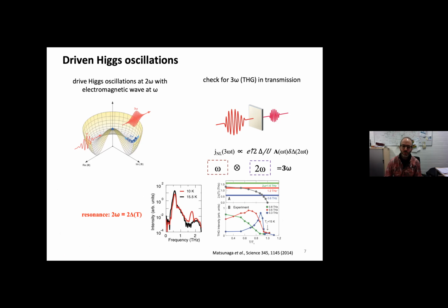And experimentally in the niobium nitride, this was also shown. So here you see this response of the system above TC in black, and then below TC. Really above TC, there's only a response at the driving frequency. And then when the system becomes superconducting, there's a characteristic third harmonic generation that comes out in these systems. And looking at this as a function of temperature, one indeed sees there is really a resonance behavior when this 2 omega equals 2 delta resonance condition is met. That is where the superconductor has the highest efficiency for the generation of this characteristic third harmonic generation.